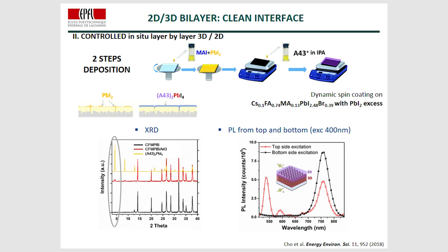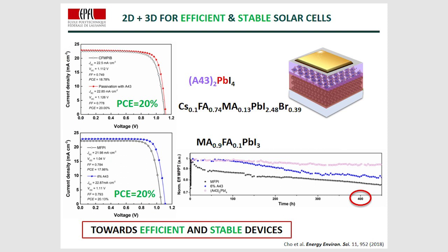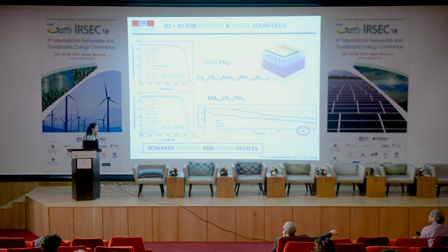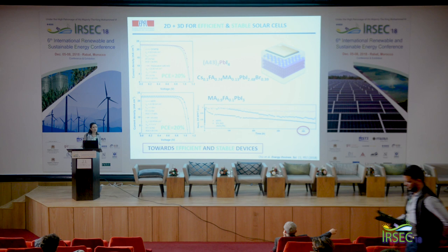With these devices, it was possible to obtain a very promising efficiency of 20%. Two different 3D perovskites were tested: triple cation (cesium, formamidinium, and methyl ammonium) and double cation (methyl ammonium and formamidinium). We already have excellent stability results of more than 400 hours, and we are still waiting for further results — we hope to achieve the same stability or even more as in the first example, giving us very efficient but also stable devices.